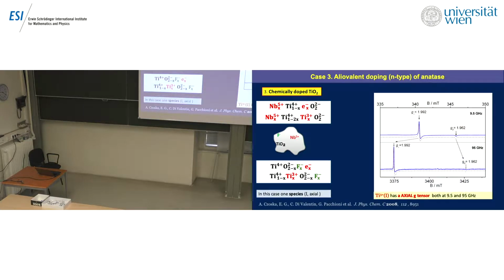So in this case we are lucky because we skip the second broad signal and we can concentrate on this kind of signal that is axial. It is actually normal EPR. If you go to higher field, we did an experiment at higher frequency, so 95 gigahertz, surprisingly, this signal is still the same, is axial, and this sends a message on the symmetry that we didn't understand at the beginning. We took quite a long time to understand that it was a problem. It was sending us a message. Anyway, let's go and see.